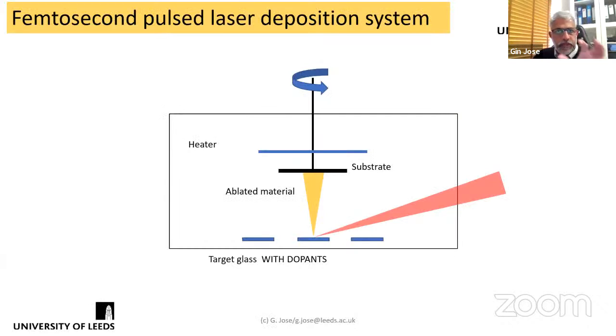So this is a simple schematic of what we do. What we have is a target material. In most of my experiments, we use rare-earth doped glasses. When you excite these glasses using a laser, a femtosecond laser, because of its unique characteristics, it ablates the material and the material gets deposited on a substrate. This is similar to any pulsed laser deposition process.